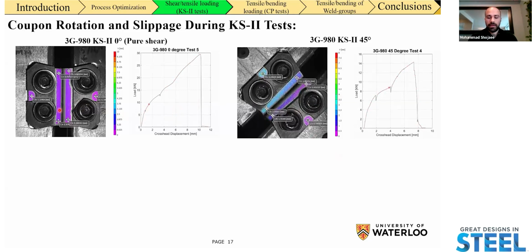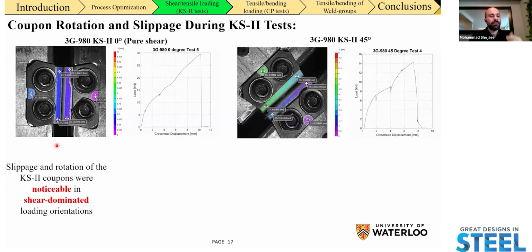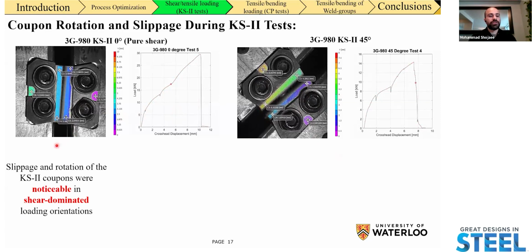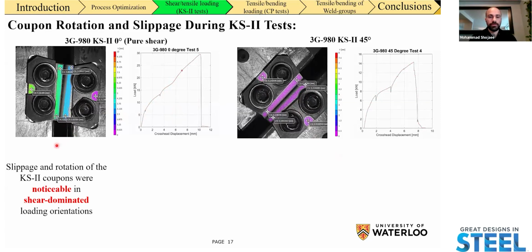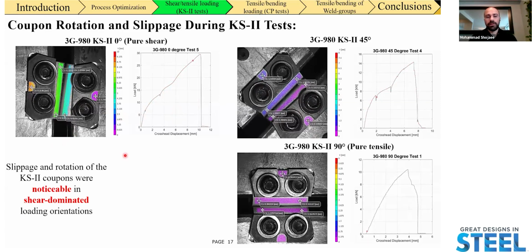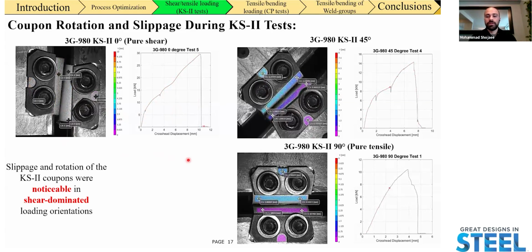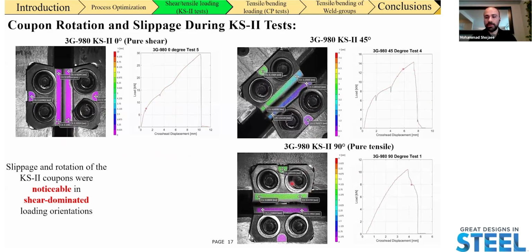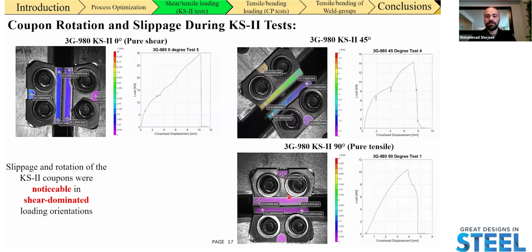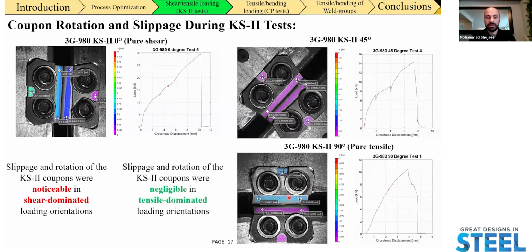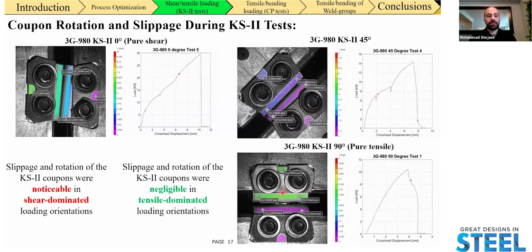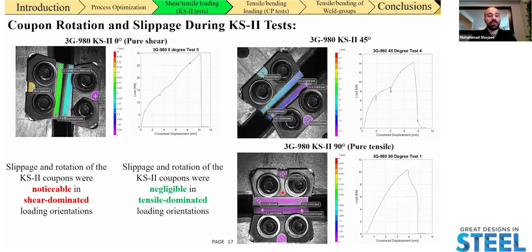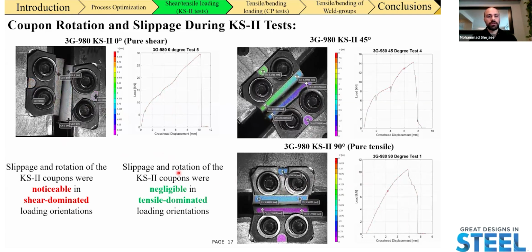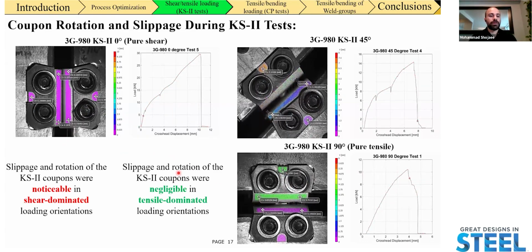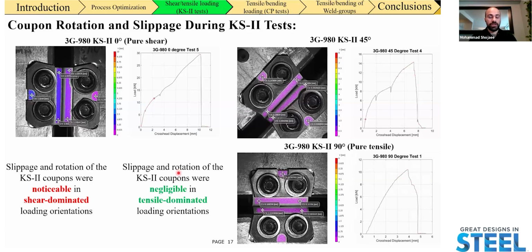Now, the issue is that as the tests continue, we have a non-negligible amount of rotation that is happening in shear-dominated loading orientation, but that's not really an issue in tensile-dominated loading orientation, as shown on the bottom right-hand side here, where we are essentially maintaining our alignment throughout the whole test. So this is not really an issue in tensile-dominated loading orientations, but it has to be accounted for when we're constructing our failure loci for shear and shear-dominated loading orientations.